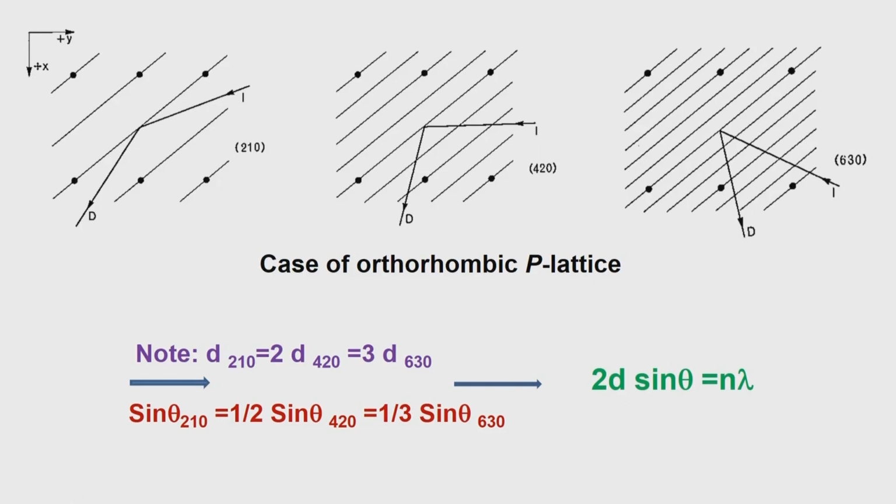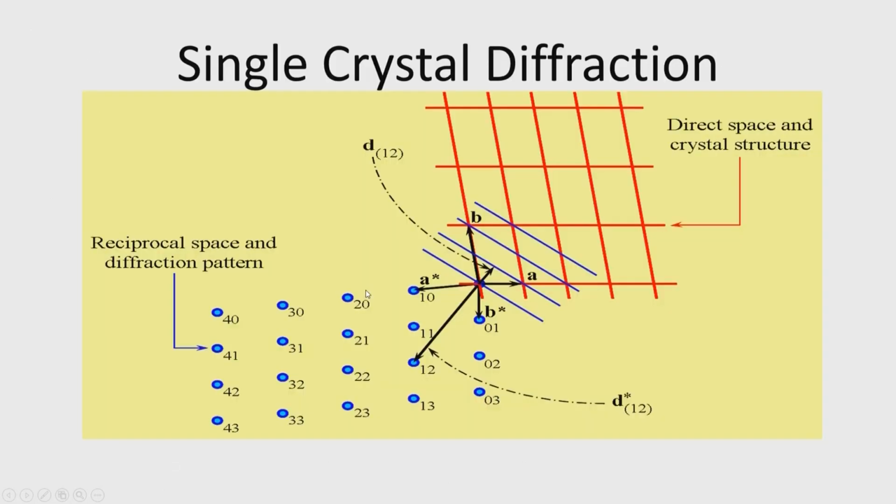But when we deal with other issues like X-ray spectroscopy, for example, all the orders will appear together, and therefore we have to use the formula 2d sin theta equals n lambda. Basically n can take different values, and that represents the so called order of the reflections. The order of the reflections comes up as a consequence of the h and k doubling and tripling here, which results in variations in the sin theta angles. Having seen this, now we will see what happens in the diffraction condition.